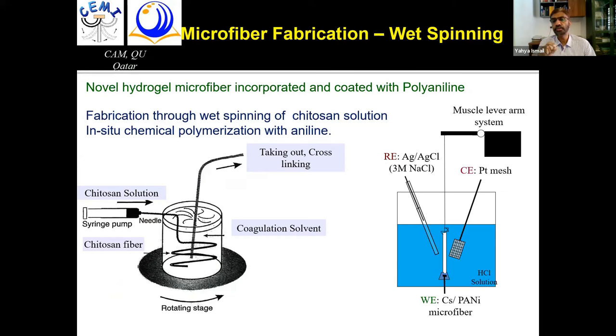And then after getting this, if you want, you can cross-link it with something like glutaraldehyde to impart some more strength. And then after that, you can hybridize with conducting polymer through in situ chemical polymerization. And after that, the fiber will be like an artificial muscle fiber. Not exactly, but to a certain extent, because in terms of actuation, it can produce both bending and linear actuation. What I did is the linear actuation with a proper muscle lever arm.